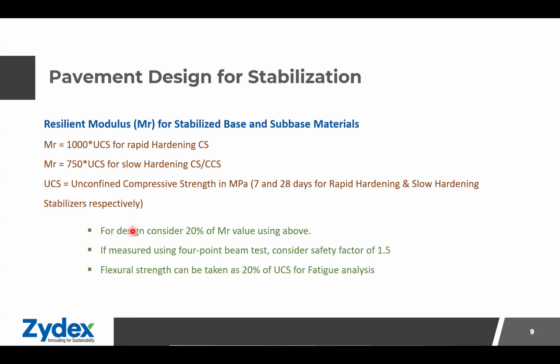Further, for design, we need to consider 20% of the MR value calculated using these two equations. If we are measuring the modulus using 4-point bending test, we need to consider a safety factor of 1.5. For flexure strength, we can take directly 20% value of UCS and use that value for the fatigue analysis.